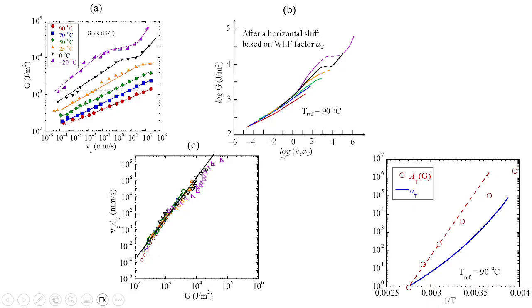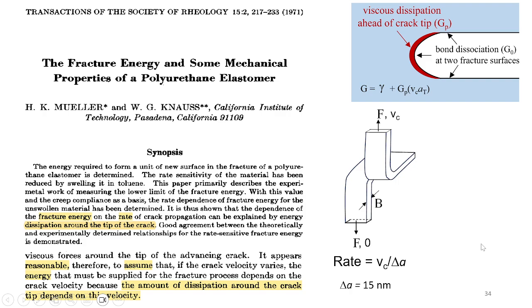So you can look at this a little closer, the very same data. You do a WLF shift, that's how you get this. But if you do a little more carefully, as I did, you find the shift is the circles and WLF is the blue line. They are not the same. That was just a minor way for me to. Yes, please. Is this for a filled rubber or unfilled? Rubber. So it's all unfilled at this point.